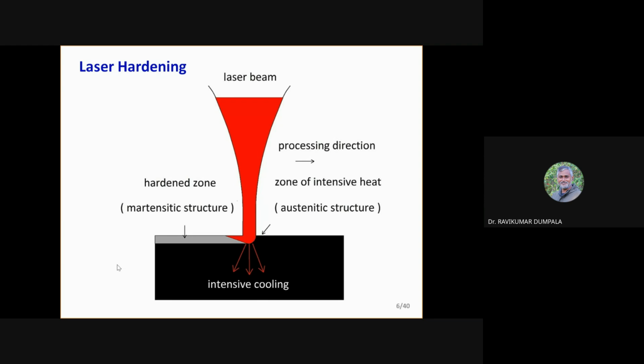It doesn't require external quenching, because the rate is so high that the top surface gets heated up to 1000 degrees, and by the time the laser moves on, it cools down to room temperature, because the base of the component absorbs that heat. So no external quenching is required. It can be very localized, and you can repeat it multiple times with the same accuracy. But it is an expensive technique, so only aerospace industry people use it. This is the very basics of surface heat treatment.